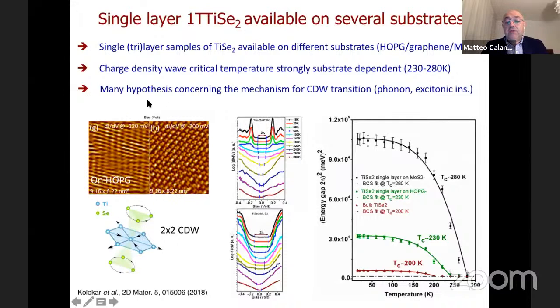And when you lower the temperature below a certain critical temperature that we call the charge density wave temperature, that depends on the substrate on which you put the titanium diselenide tri-layer, I will tell you in 1 second, what happens is a 2x2 reconstruction. Of course, it's a 2x2 charge density wave that is illustrated here.